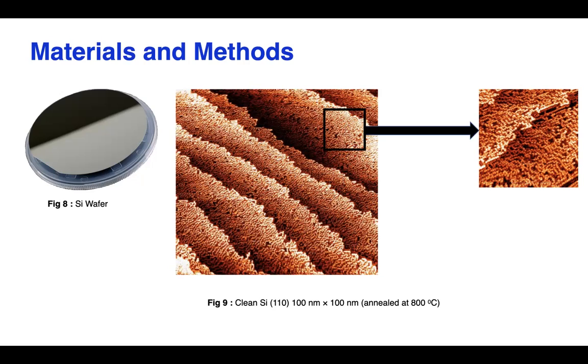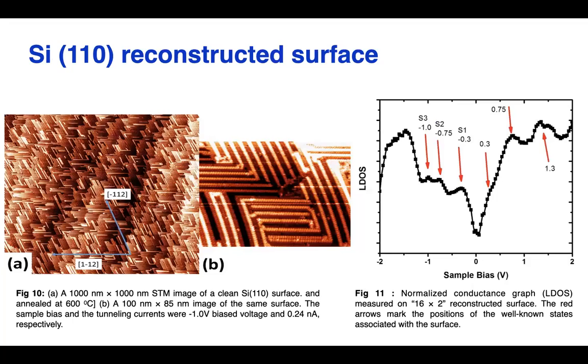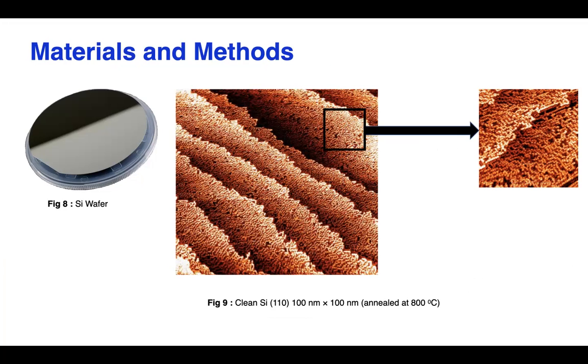After flash annealing, this is what it looks like, but we still did not get the reconstructed structure of silicon 110, because you can see this is a disordered form of silicon 110. There are lots of step edges on the surface. In the second image, a high resolution image, you can see small spheres. Those are silicon atoms. But this is not what we want, because we want the silicon 110 reconstructed structure.